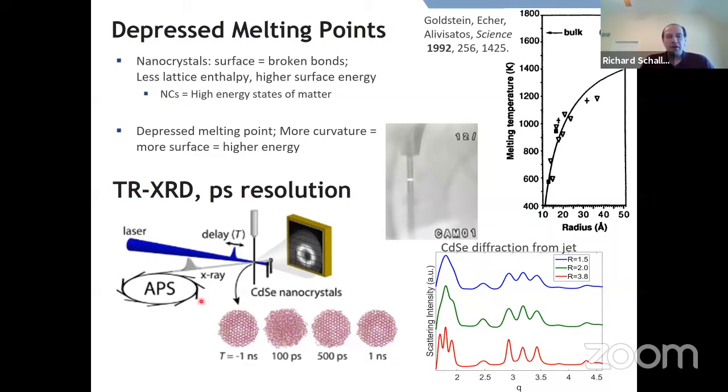And then we take the synchrotron, which is a 6 megahertz source of X-ray pulses that in different modes of operation can be a lower rep rate, but also we can do things like gate detection of it. We take an X-ray pulse and have a time delay between the pump pulse and the X-ray pulse. And they both cross the sample in the same location. And then the X-rays go through the sample, and I'm going to tell you about how they diffract and create these what look like ring structures out here.